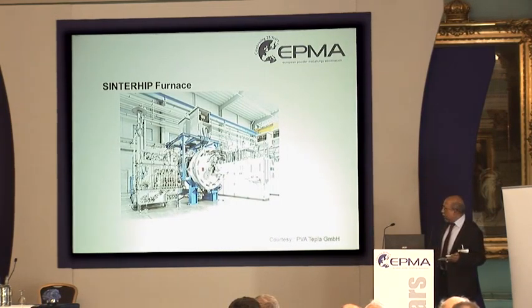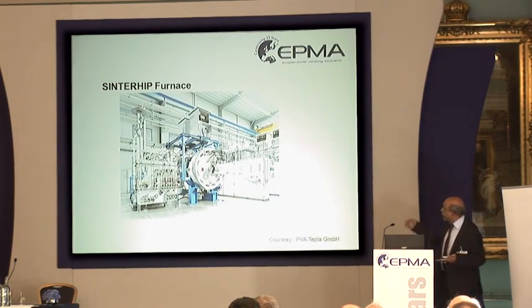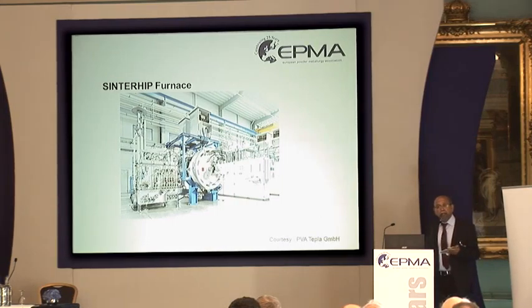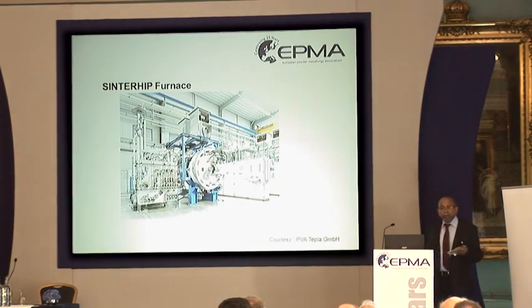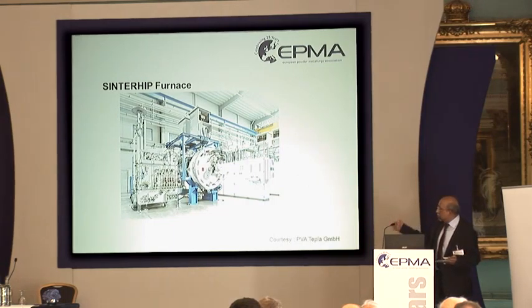And the real breakthrough came with a sinter-HIP furnace, which is also the same size. And this sinter-HIP furnace leads to the fact that anybody can make good hard metal if the starting raw material is good. In the early days, we had to be very careful about choice of starting material, carbon content, and whatever. Nowadays, with a sinter-HIP, we are also able to use a lot more recycling material.